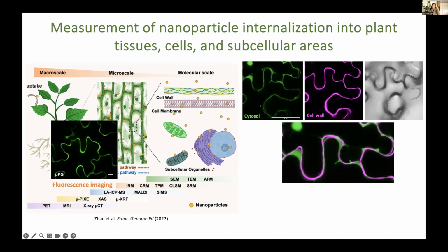So what we can do and what we do in our lab is that we use a high resolution, high magnification, high zoom, different imaging approach that enables us to start separating the two cytosols of neighboring cells. So you start seeing this little gap in between two cytosols, which is where you have the cell wall, and we can use a cell wall stain, and you'll see that the cell wall does not overlay with cytosol, which will be very helpful to see if your cargos are actually in the cytosol inside the cell, or they're getting stuck by the cell wall. Even though this works, it's not always easy to be able to image like this. It takes a long time, and it doesn't work when you have thick samples.